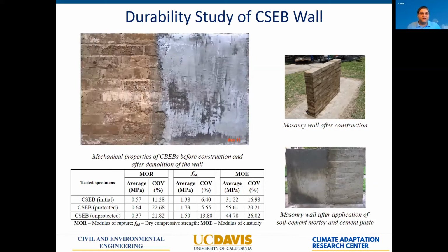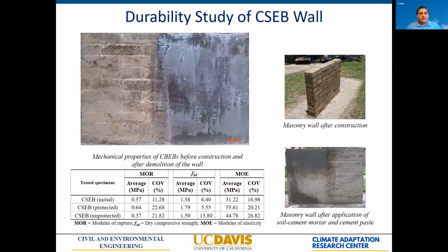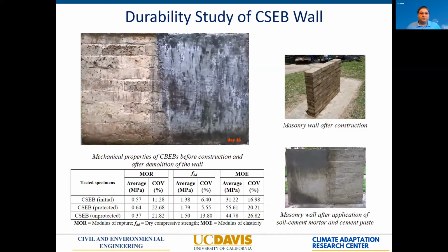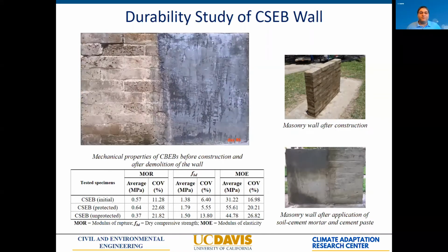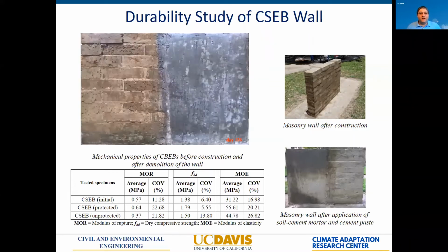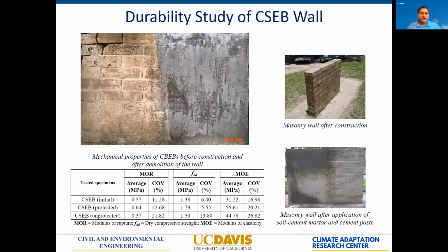And as you can see in this time lapse, indeed, the side that was not protected started having issues pretty early on with the rain that is really excavating the mortar, particularly at the top corner. And once the mortar is removed, you can see that the masonry is damaged, the block is damaged and broken. However, on the side that is protected, we didn't find any damage.